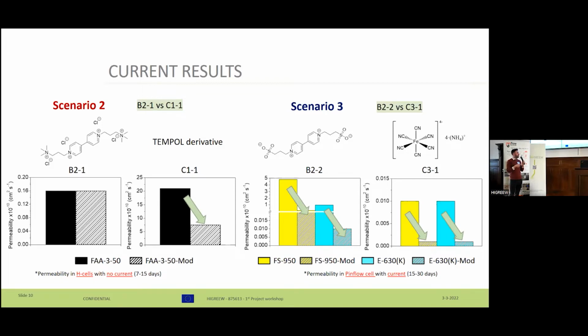I would like to point out that in the scenario 3, the permeability values, among further tests that we have performed, were done in a redox flow cell with a certain flow rate and applying current, and during 1 month of evaluation, which is also important to foresee the lifetime of our membrane and battery prototype ultimately.